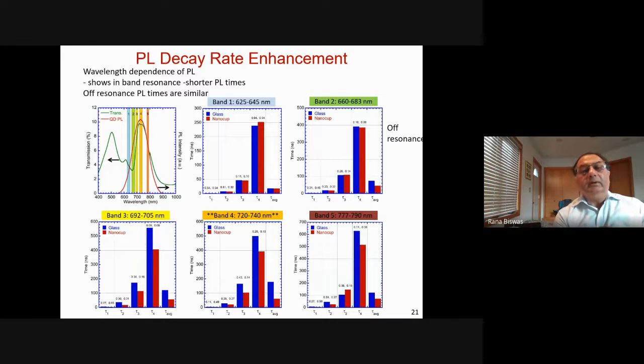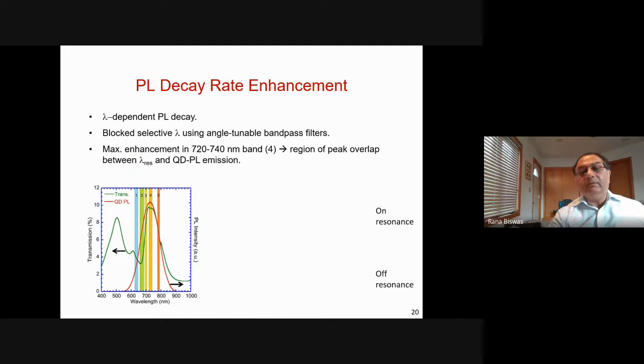So it's of interest to look at the wavelength dependence of the photoluminescence. So you can either sit out of resonance. So when you're at band 1 or band 2, you are outside the resonance peak. So that's the blue or the green bar here. And you see then the glass and the nanocup are more or less having the same average decay time. But when you go in resonance, band 3 or band 4, around 700 nanometers, that's when you see this marked difference in the decay times of the nanocup. So this is what makes a difference in the resonant behavior.